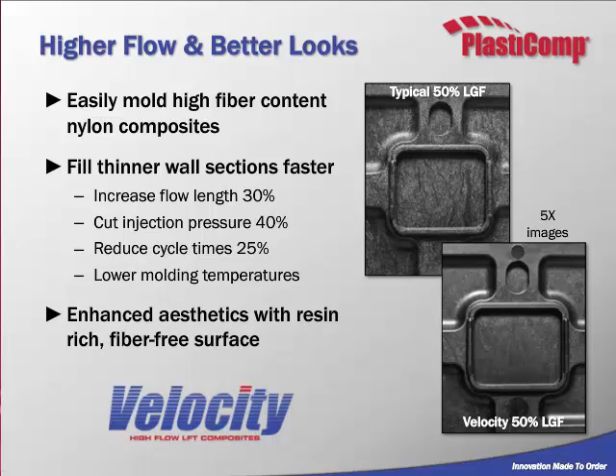So with the Velocity grade, this will give you the ability to have a better looking surface at these higher filler contents, and also if you're having difficulty filling a thin-walled part, this material may be the answer. I've also noticed in certain cases where molders were able to reduce the temperatures that they were processing at, which helped improve cycle time while maintaining part aesthetics.